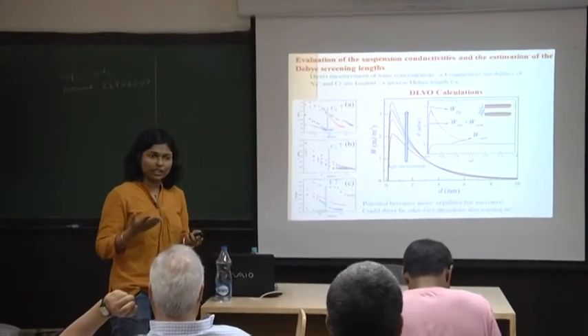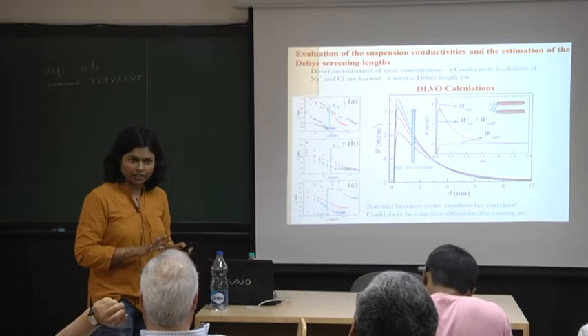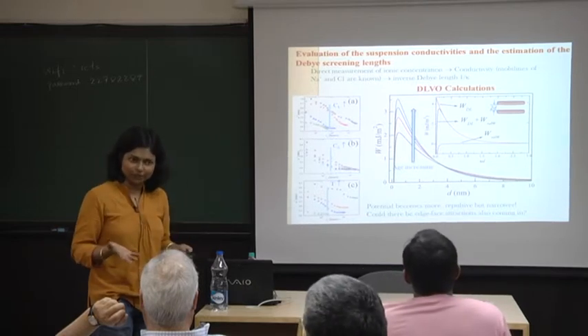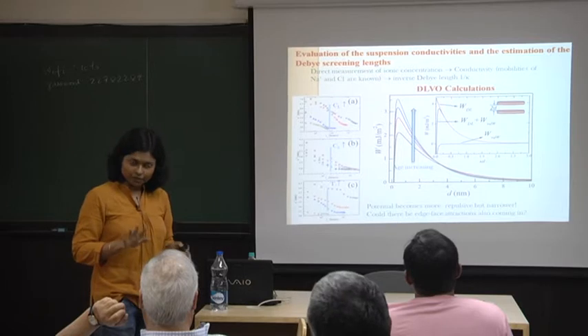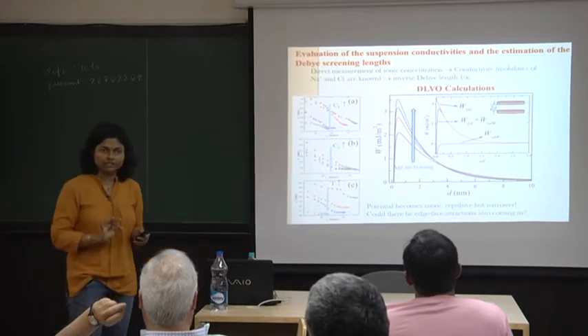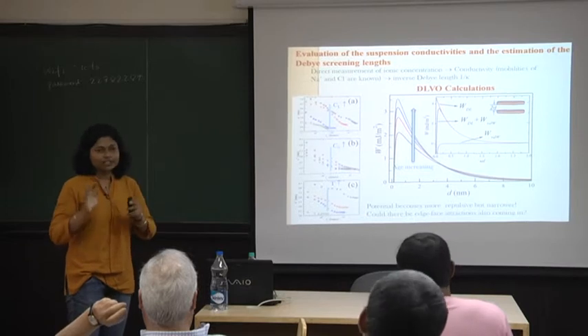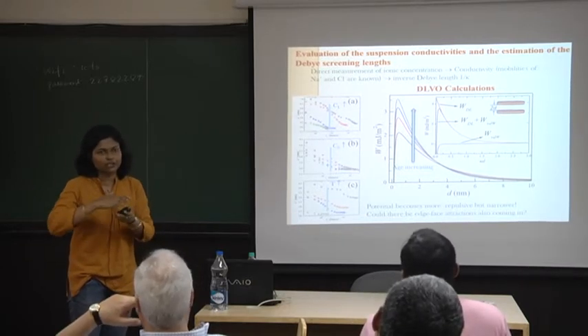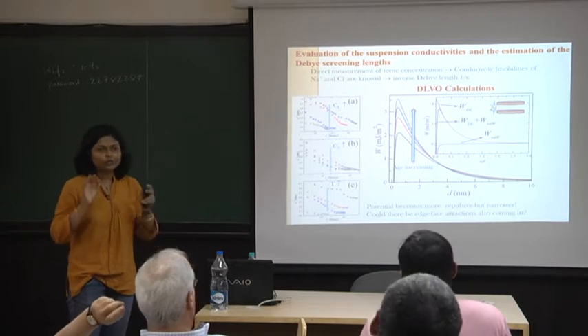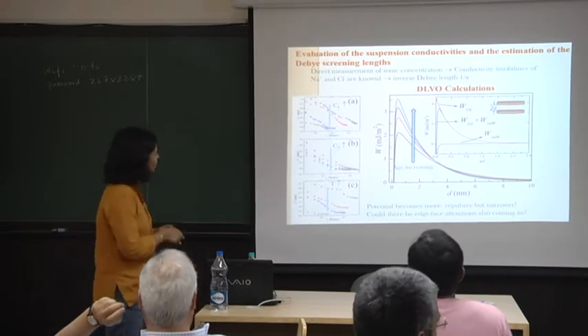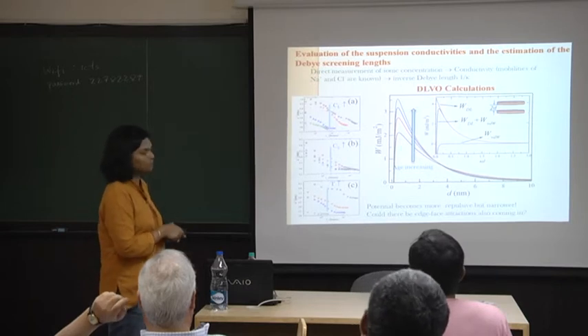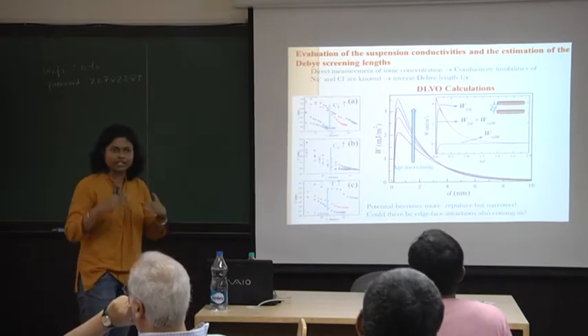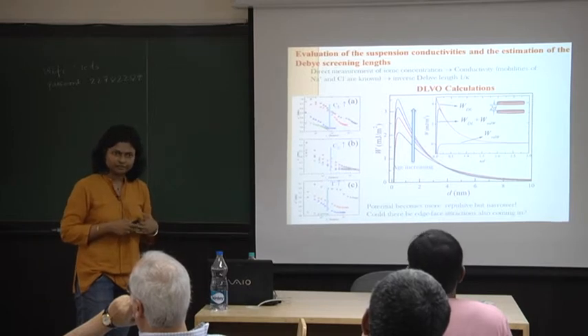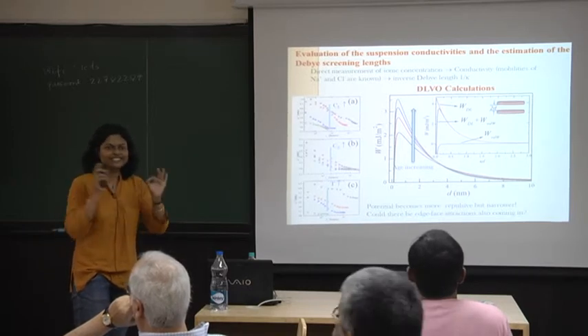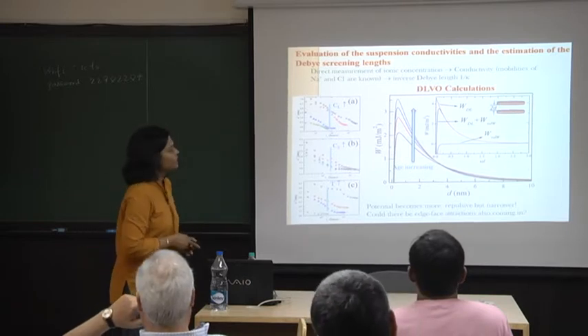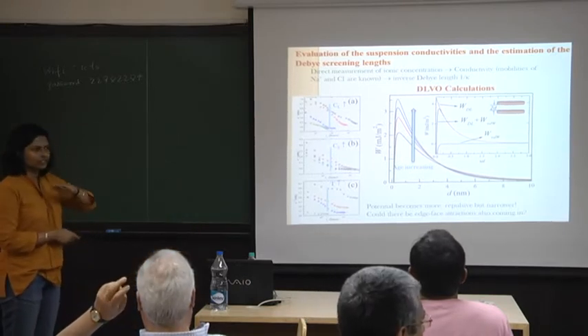We're not worried about exfoliation anymore, because exfoliation increases the sodium ion concentration. We are measuring the increase of sodium ions in solution, whether it's coming from exfoliation or something else, we're not interested in. We just measure the sodium ion concentrations because we want this value for the Debye length, so that we can plug it into a DLVO model and calculate an interplatelet interaction. We're not interested in the specific details. So we've done this for all our samples.